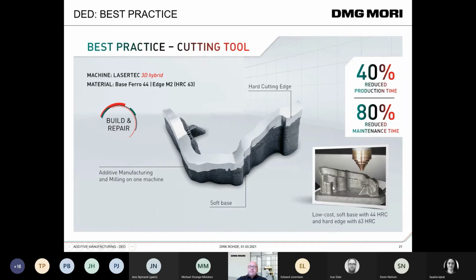Total print time of this part here right in the bottom, including the hard cladding and machining, is 6.5 hours. So you get completely away from this machine tourism where you machine the destroyed sections off and move it to the next machine or to the hand welding shop, and then relax or stress relieve it and then finish it. And it takes typically for this customer 3 to 4 days for replacement. With this case, he has it in less than a shift, completely replaced and ready for the assembly.